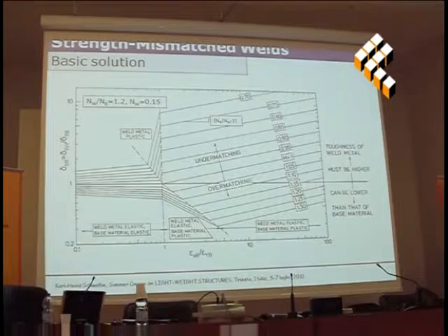And that's why it shows immediately, I think without any further thinking, why in our first example the crack ran into the high toughness austenite. The austenite has a much lower yield strength than the base plate, and accordingly a much higher driving force, and so the explanation is there.